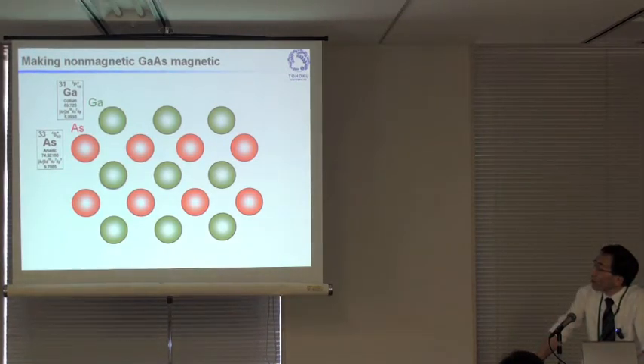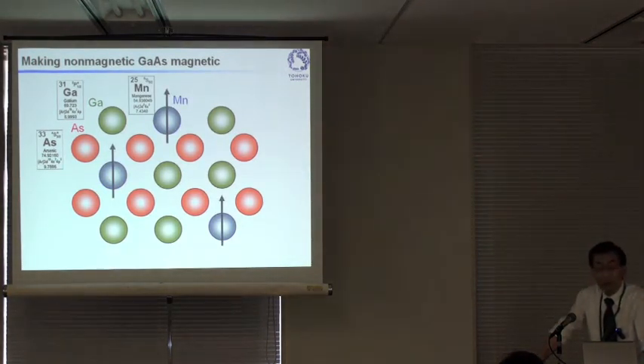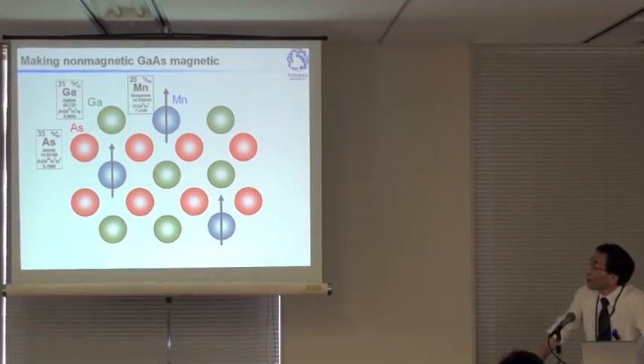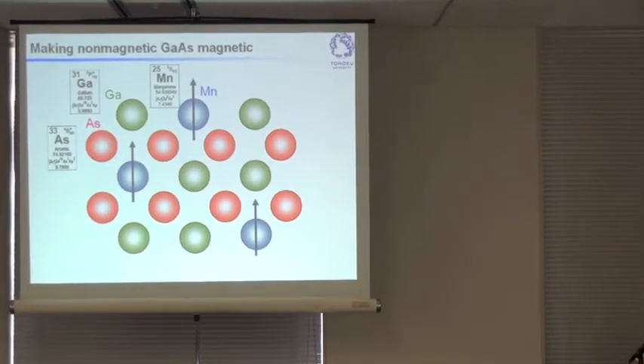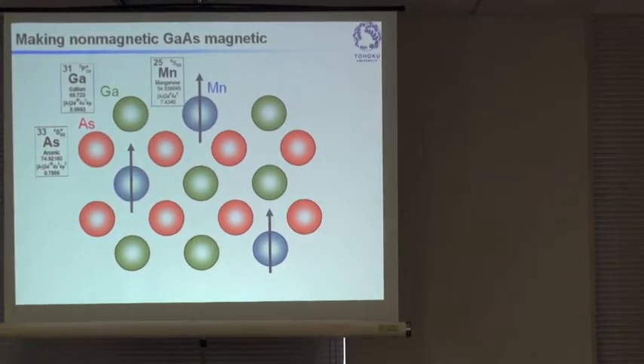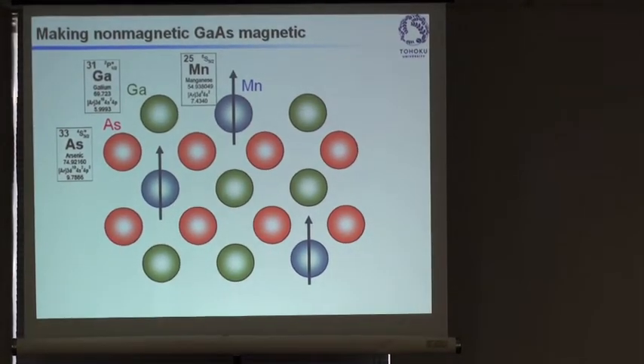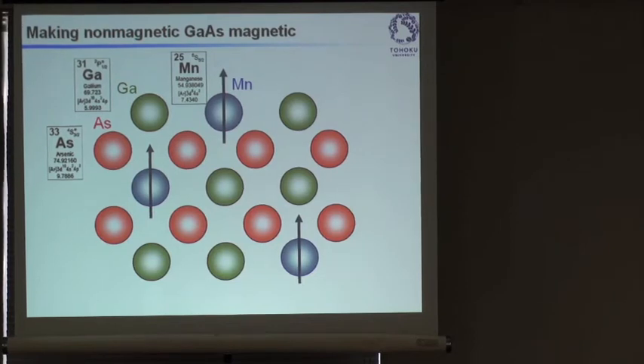So the choice was to put some manganese into the system, partially replacing gallium. You can call it doping, but we wanted to make this doping as high as possible to see the magnetic effect. So we wanted to go beyond the solubility limit. Now, parenthetically, manganese has only two s electrons, and when we replace gallium with manganese, there's one missing valence electron. So manganese not only introduces 3d electrons, but also introduces a hole, a conduction carrier.